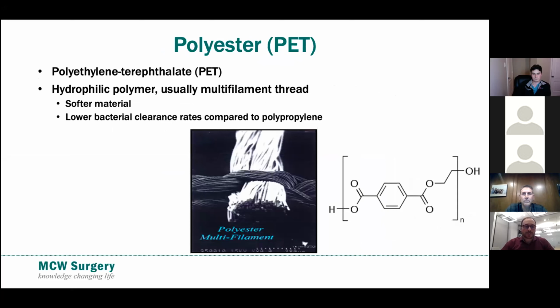Secondly, polyester. The ester that's most commonly utilized with mesh repairs is ethylene terephthalate. That's just the ester group. It's a more hydrophilic polymer. Typically it was multifilament thread. However, there are now monofilament constructs available as well. It tends to be a little bit softer of a material, and with the multifilament constructs in particular, tends to have lower bacterial clearance rates compared to a polypropylene.